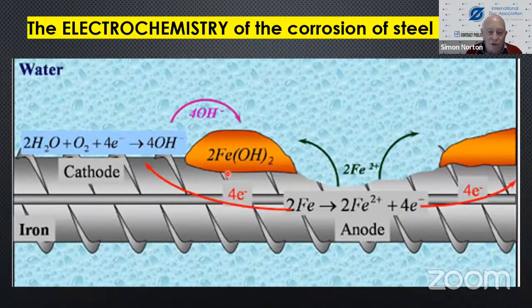The electrochemistry of the corrosion of steel in water, or in an aqueous solution, as we call it. There's always a corrosion cell available that happens or occurs where corrosion takes place. And in particular with steel, you'll have an anode and a cathode. But that applies to other corrosion as well, on aluminium, on copper. I'm just using the example of steel because we're going to coat it with zinc. So at the anode, iron is oxidized to what we call the ferrous ion. So iron naught goes to iron plus 2, and it generates 4 electrons. Those electrons are then transferred across to the cathode.